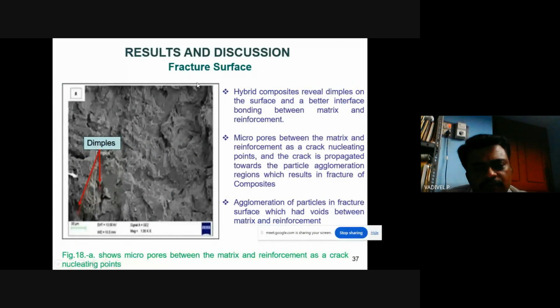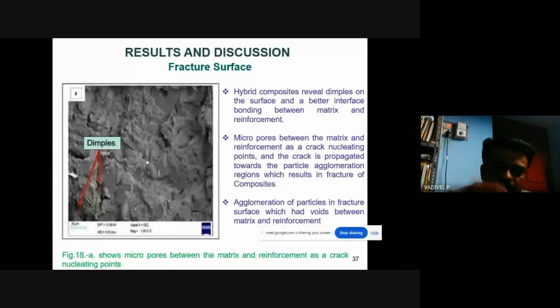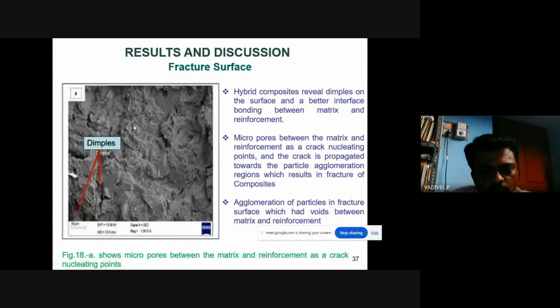And now coming to the fracture surface of the hybrid composites. Here you can see the micro pore holes, which are crack nucleating points. The fracture surface shows the same result. You can see some dimples, in the sense that there are some valleys. It is like if we break a chalk piece, the cross section of the area will not be uniform. There will be some holes or projections. So we can see the dimples here.